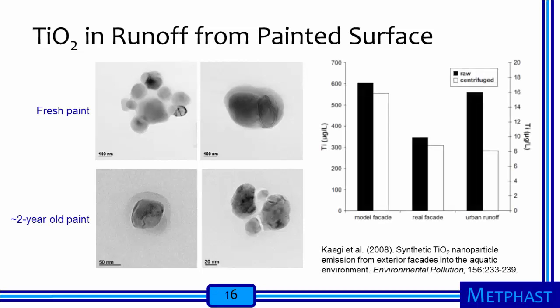This figure shows titanium concentrations in the runoff from the freshly painted surface, the runoff from the surface painted 2 years previously, and in urban runoff waters. The concentrations for the newly painted surface are shown on the left vertical axis, whereas the concentrations for the older surface and the urban runoff are shown on the right vertical axis. The total raw concentration of titanium in the runoff from the freshly painted surface was about 600 micrograms per liter. When the runoff sample was centrifuged to eliminate particles larger than about 300 nanometers, the remaining concentration was about 550 micrograms per liter, indicating that the overwhelming majority of the titanium mass in the runoff was associated with particles in the nanoscale or near nanoscale range.